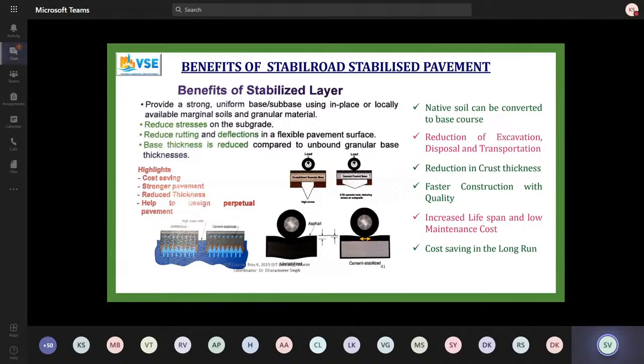The highlights again: one more important thing is a reduction in thickness of pavement. Because our layer is so strong, the modulus is pretty high. Because of that, using IITPAVE, we can bring down the thickness of DBM and BC to a large extent.